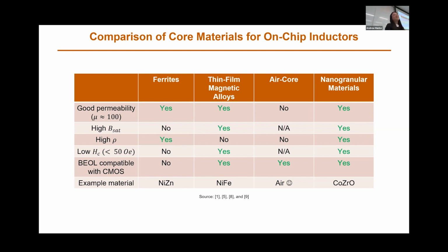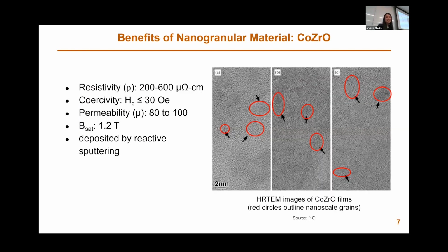And basically they check all the boxes we want. I'm just going to focus on one particular nanogranular material, cobalt zirconium oxide. Cobalt zirconium oxide consists of these cobalt grains that are nanoscale. They have to be nanoscale so that they're small enough to not have that much eddy currents flowing inside them, which leads to its high resistivity. These cobalt grains are surrounded by an inactive insulating zirconium oxide, and that's generally how these nanogranular materials work.